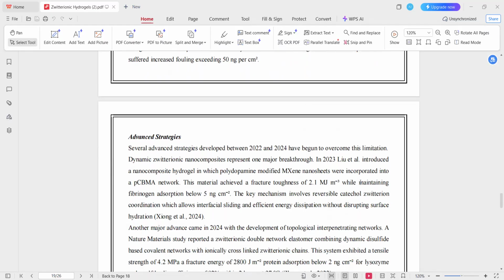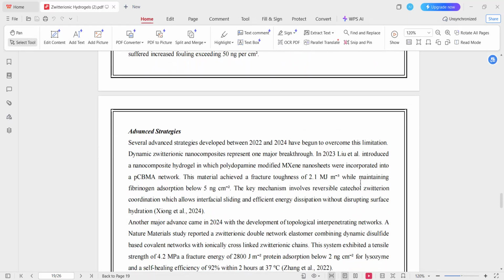One of the major breakthroughs in overcoming this challenge is the development of dynamic zwitterionic nanocomposites. In 2023, Liu and co-workers incorporated polydopamine modified MXene nanosheets into the carboxybetaine methacrylate hydrogel network. This material achieved a fracture toughness of 2.1 megajoules per cubic meter while maintaining fibrinogen adsorption below 5 nanograms per square centimeter. The key mechanism here is reversible catechol-zwitterionic coordination, which allows interfacial sliding and efficient energy dissipation without disrupting surface hydration.